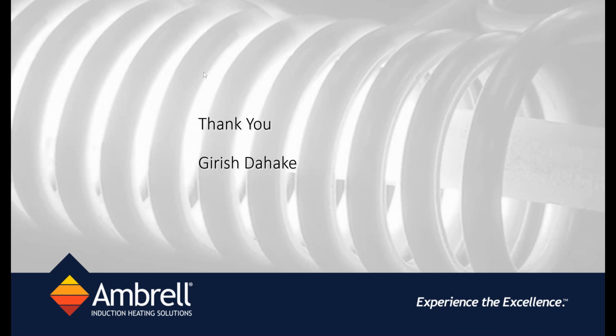So if the metal part never sees air and it's able to quench the metal part quickly inside the water, I suspect that you should not see much oxidation on the part. It is usually the transfer between the inert environment and the water environment that you get that oxidation. However, if the inert cover is over the water, you may not get that oxidation. I don't have personal experience with it. If it is still a problem, you could use an oil to do your quenching, which should eliminate all the oxygen in the area. Thank you.